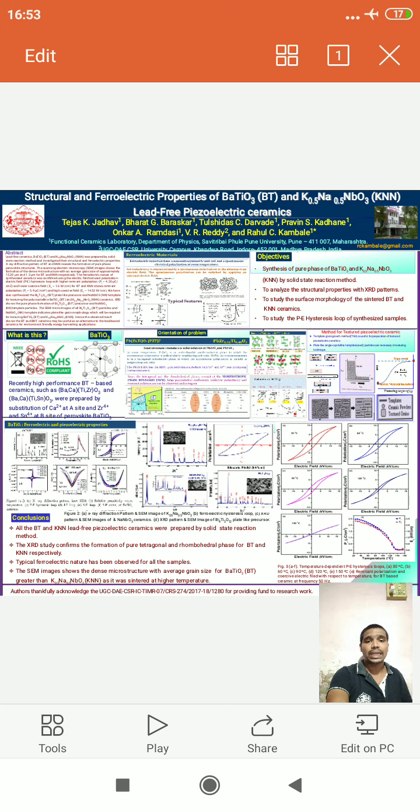We know BaTiO3 also shows good piezoelectric properties. So here we also mention textured piezoelectric ceramics. Texturing is a method useful to enhance the piezoelectric and ferroelectric properties of ordinary polycrystalline material. So after texturing, the grain growth of the polycrystalline material is oriented.